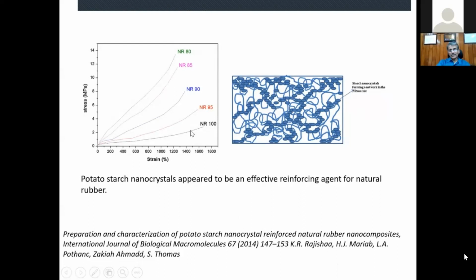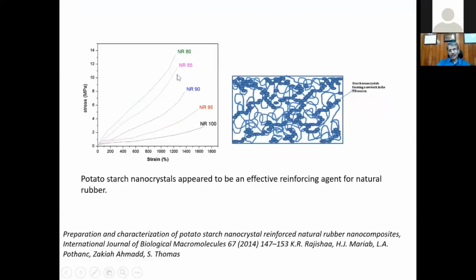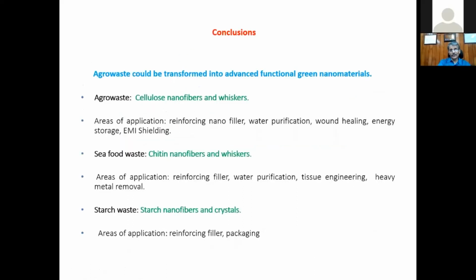And if you put increasing content of nanocrystals of starch, you see the modulus goes up. Rubber is transformed into a high modulus material. You can see a beautiful cartoon made by the PhD student. You can see the macromolecular chains and network of nanocrystals of starch, which actually immobilize the macromolecular chains. You get a very high modulus and strength.